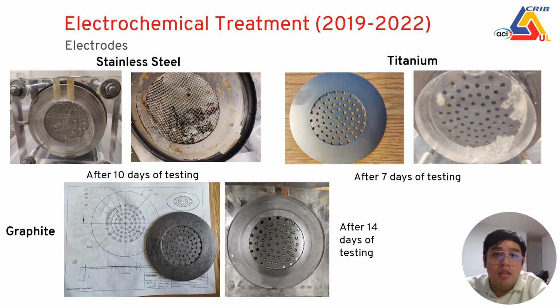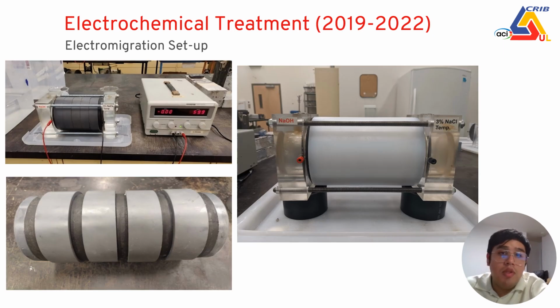So the next step was to develop the electromigration setup because we have some setups already for the RCPT, but we need a long length of the concrete specimen so we can try different testing later to evaluate the damage or the detrimental effect of the sulfide-bearing aggregates. And here you have a picture of the final setup that I developed for these purposes.